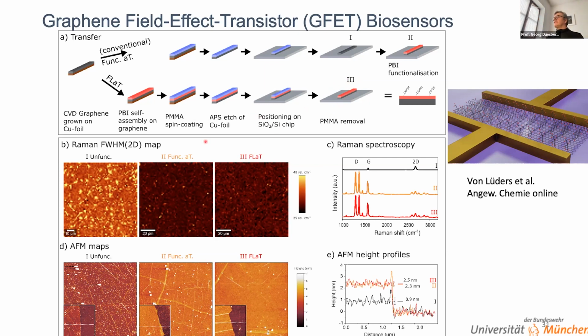And below you can see the difference of this functionalization route in direct comparison in the AFM and Raman maps shown here. This is the unfunctionalized material, which actually looks the dirtiest. The functionalized material with the conventional method: we get a decent surface at the end, but you can see quite a few remaining residues. And if you do this, what I call flat, this functional layer transfer, we actually get a very flat surface, which is fairly pure and on average a bit flatter than the other surfaces, meaning a bit more homogeneous.